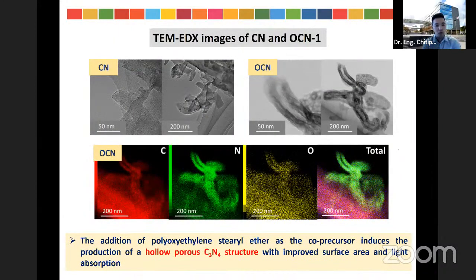And we observe the morphologies at lower magnification by using the TEM, and it was found that the CN sample, or the pristine graphite carbon nitride, shows a sheet-like structure. But when we have the co-precursor of the POS, or the oxygen-containing polymer, as a template and oxygen source, the needle-like structure or tubular structure of the graphite carbon nitride can be observed like this. And the mapping result of the oxygen-doped sample shows the overlapping of the oxygen atoms in the same location as the carbon and nitrogen, indicating that the utilization of the POS as a template and oxygen source can produce the oxygen-doped hollow porous graphite carbon nitride.